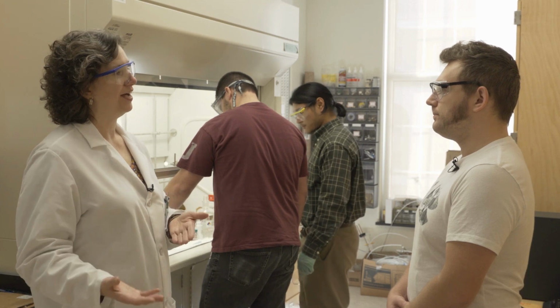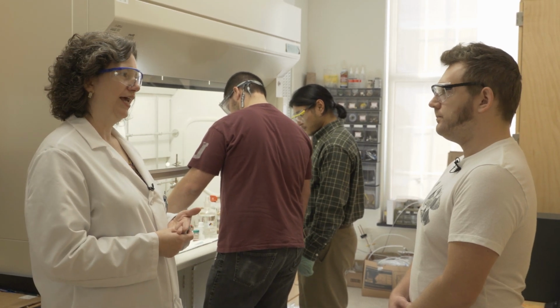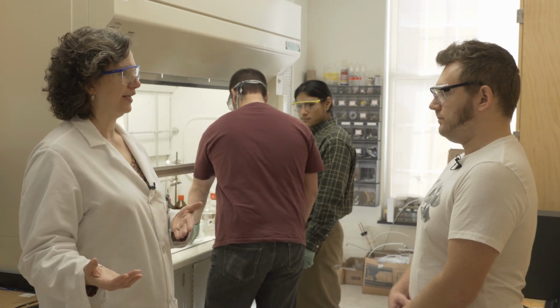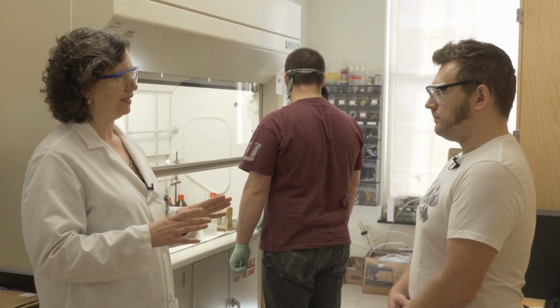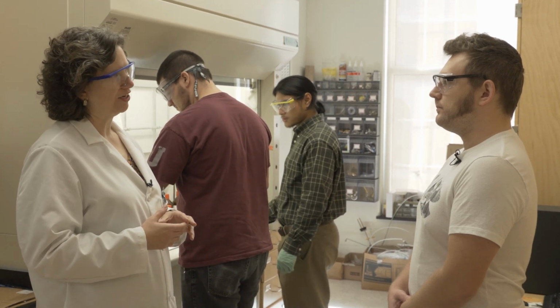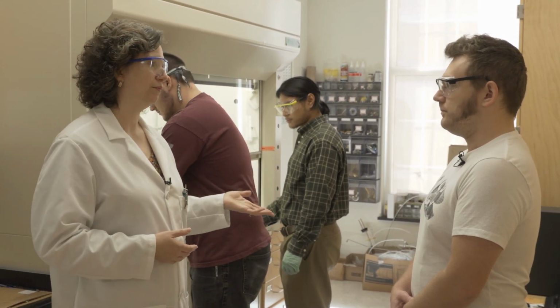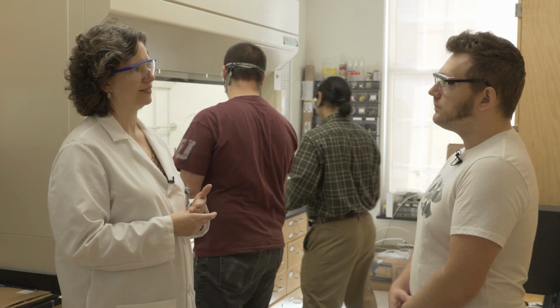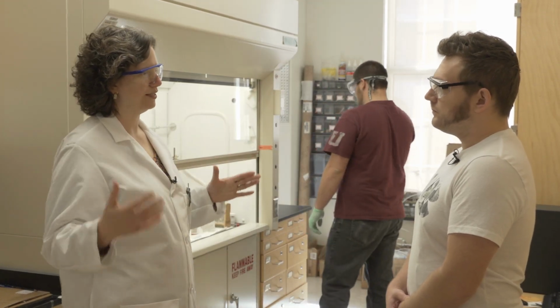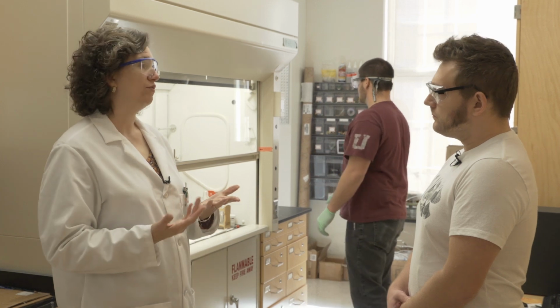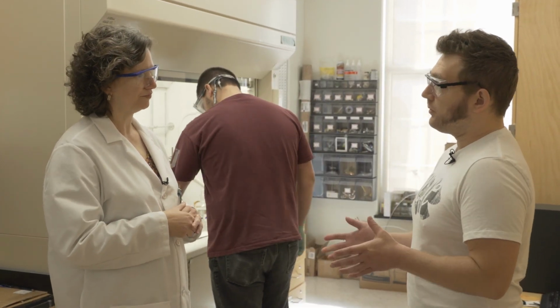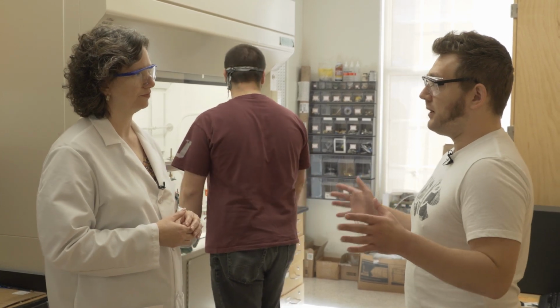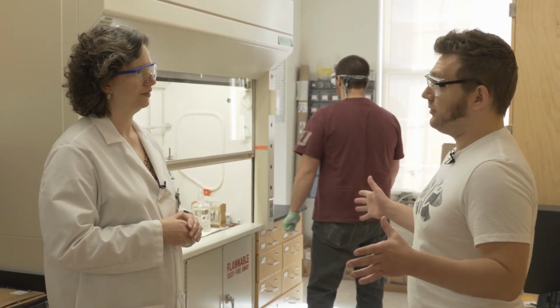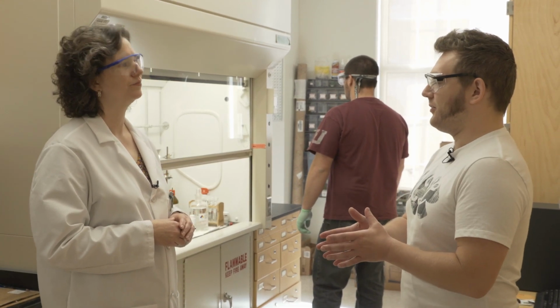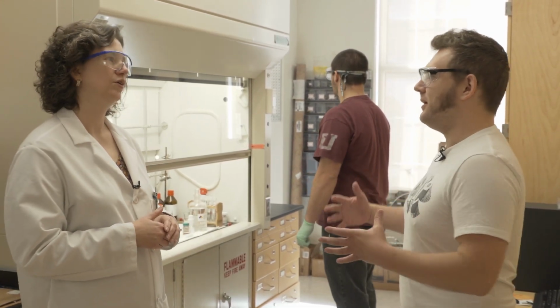And our method does not involve solvent exchange. It's a direct method, and so there's a big advantage in terms of scaling up. We're able to make monolithic materials, so single piece materials, using a method that's inherently scalable. We're using laboratory scale hot presses, which we'll be showing you here, but there are industrial hot presses that are simply enormous, and so this process can potentially be scaled up to window-sized pieces of monolithic silica aerogel with very good optical transmittance. Whereas supercritical dryers are not typically bigger than a few feet in diameter on the industrial scale, and the wall thickness scales unfavorably with diameter of the inside of the autoclave.